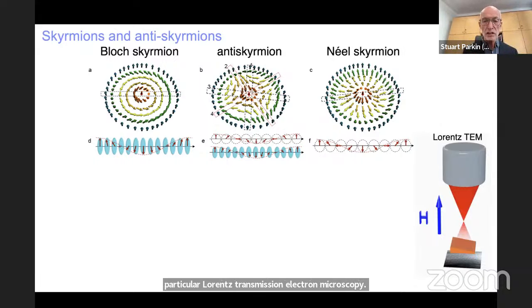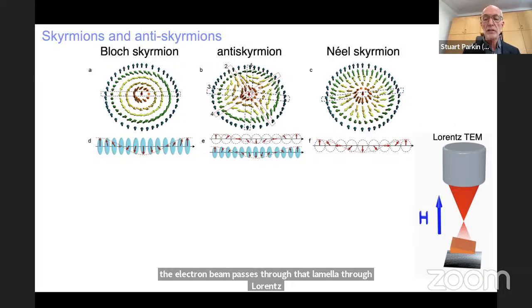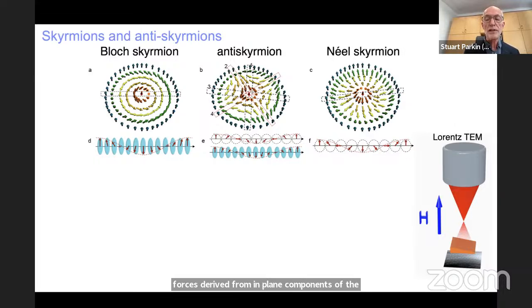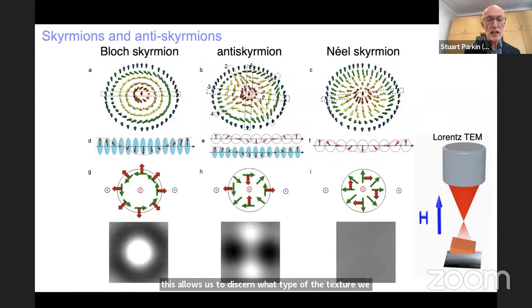In this case, we take a single crystal and we use focused ion beam milling to mill out a lamellar thin sheet, which is sufficiently thin that an electron beam can be transported through it. We need a beam energy, in our case, of 200,000 volts. Then we place this lamella in the electron beam, and as the electron beam passes through it, through Lorentz forces derived from in-plane components of the magnetization, the electron beam will be deflected, and this allows us to determine what type of texture we have. At the bottom, this is the image we expect to see in this Lorentz microscope, depending upon whether we have a Bloch skyrmion, an antiskyrmion or a Néel skyrmion.